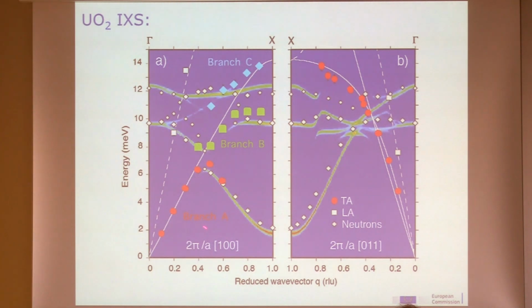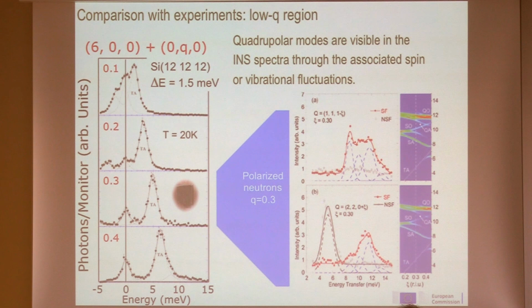So here is again the results superposed to the magnetic intensity map. You can recognize easily not only the anti-crossing here, but also here. You can observe here peaks that are due to the hybridization with acoustic quadrupolar waves and optical quadrupolar waves. For instance, you can compare the consistency of the results. For instance, look at these peaks. This is the same excitation.